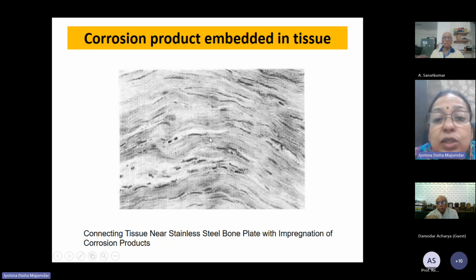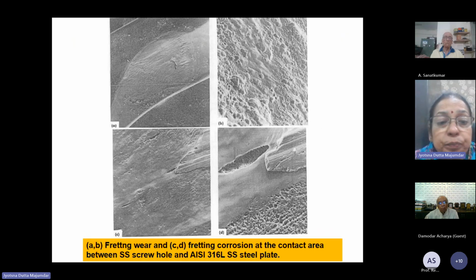If you see all the tissues, they are covered with the corrosion product. So clearly it is carrying the corrosion product. If you talk about 316L stainless steel, there is chromium oxide corrosion product, which is just a film, which basically dissolves gradually. Sometimes there is dissolution of nickel as well, which is highly toxic in nature. So this oxide product as well as ions typically cause inflammation, as well as allergic reaction, which subsequently is not good for human health too.